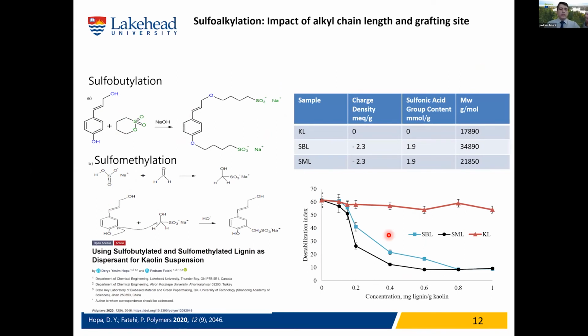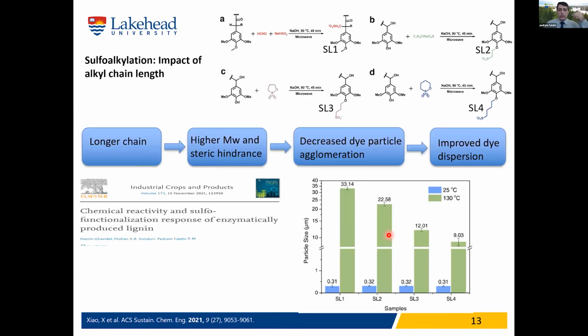So we tried different sulfoalkylation. And what we noticed was that it really matters how you sulfoalkylate lignin, even if you manage the same charge density, even if you manage the same, let's say, sulfur content. It really matters what chemistry you use and how you modify the lignin. And again, some other people tried different sulfoalkylation, and what they realized is that by extending the chain length, you are making a little bit higher molecular weight, and then you will decrease the agglomeration because of the dispersion and so on. So that's another group proving our point.